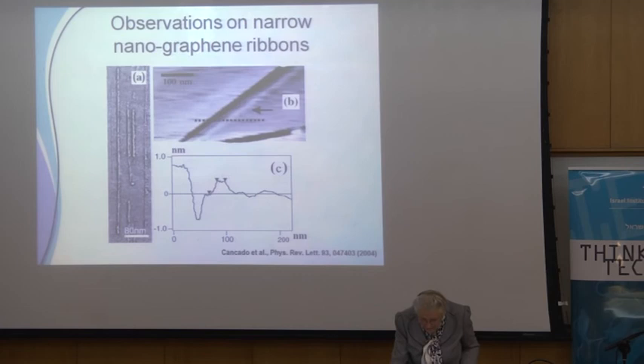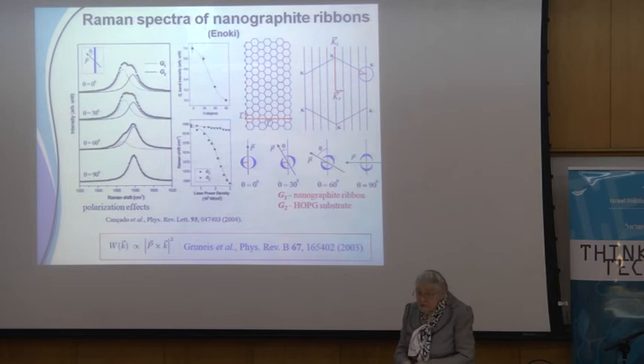Okay, so here's a ribbon. And now we're back in the laboratory. This ribbon is about 8 nanometers in width, and as you can see, it's long. This is 80 nanometers, so it's a few hundred nanometers long. This measures the geometry, and a measurement of the spectra is shown over here. You could see that the ribbon spectra is shifted from the spectra of the substrate, which is graphite, and the ribbon is a graphene ribbon.